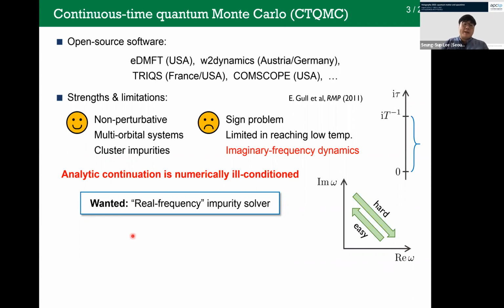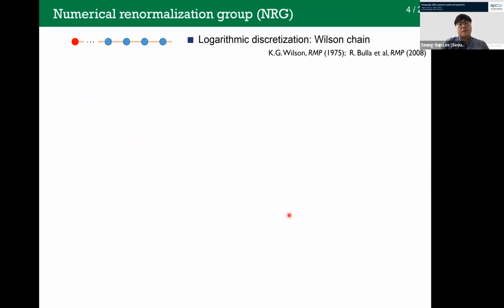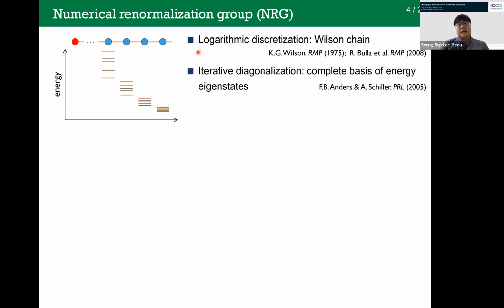So in this regard, we need a so-called real frequency impurity solver that can provide dynamical properties directly on the real frequency axis. There are some methods that can do this job, but I choose to use the numerical renormalization group for several reasons. The NRG calculations start with discretizing the bath in energy space on a logarithmic grid. The discretized system is mapped onto a semi-infinite tight-binding chain, which is called the Wilson chain. And its energy states can be constructed via iterative diagonalization.